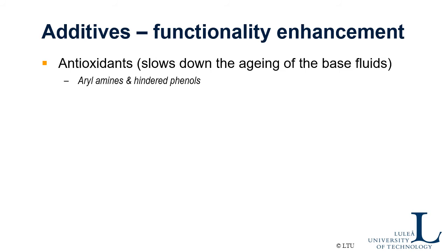Then you put the antioxidants in, and the antioxidants neutralize this process, and so the acids, for example, formed, they neutralize the acids, but at the same time they are consumed. So after some time the antioxidants are consumed. So you must have a sufficient amount of antioxidants to not consume them before the end of life of the component or the lubricant.